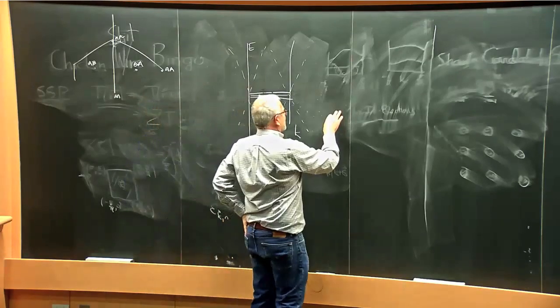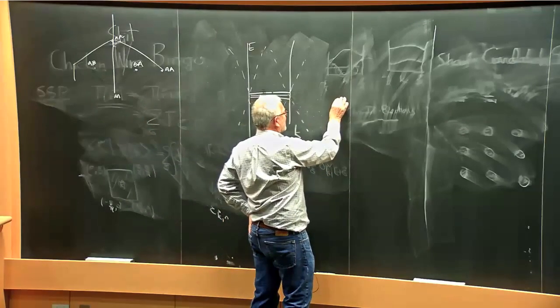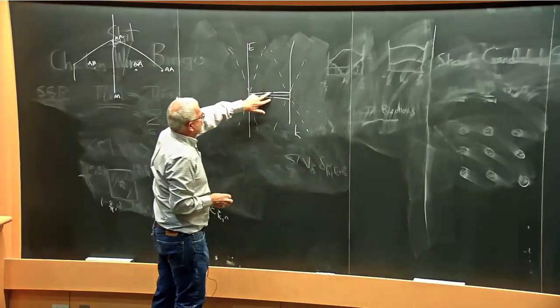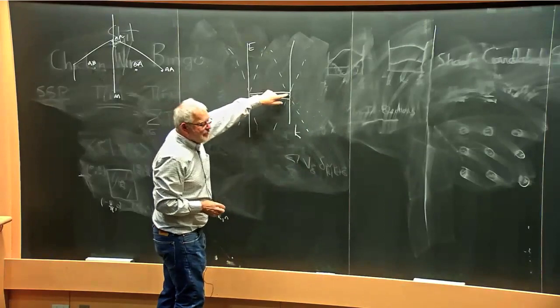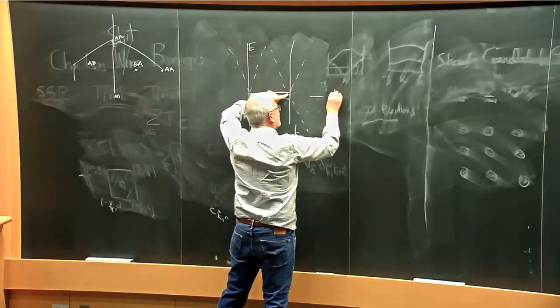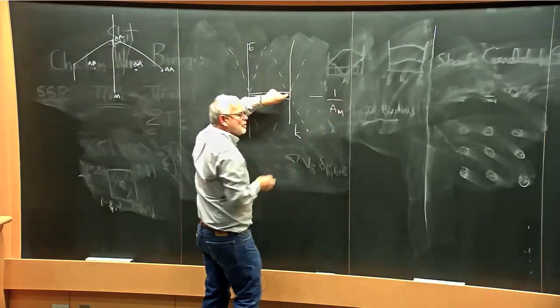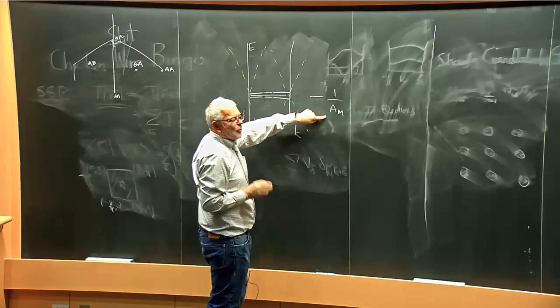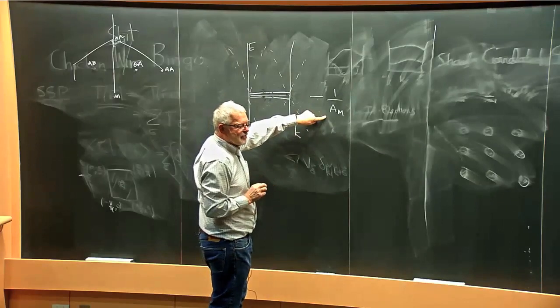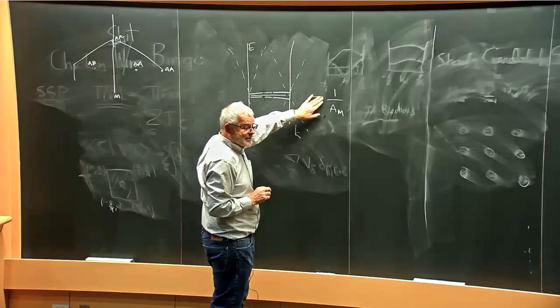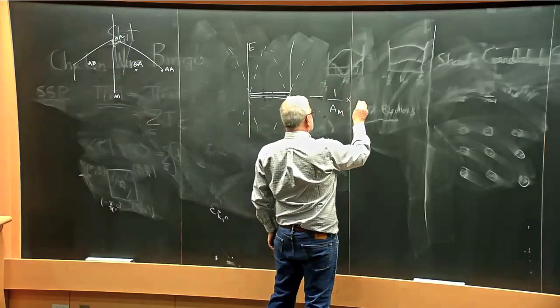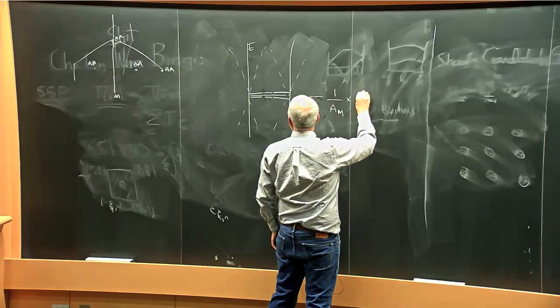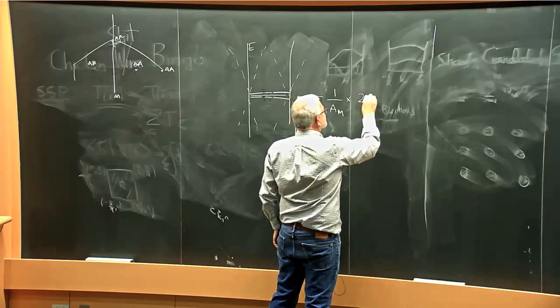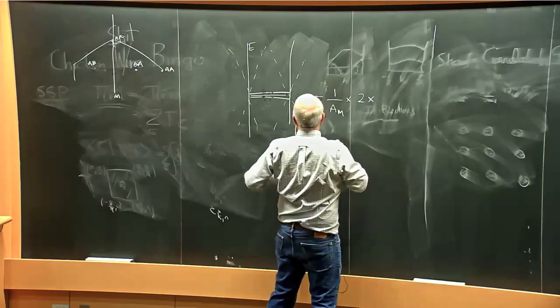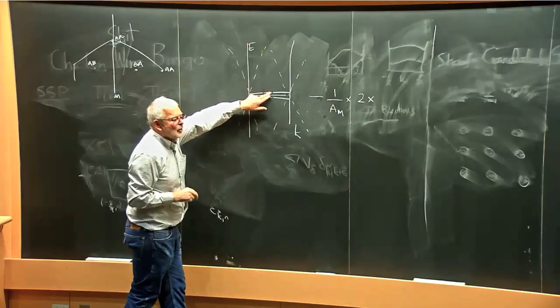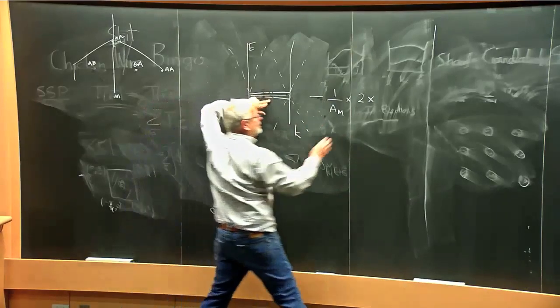And so this occurs, the number of electrons that fit in these bands is 1 per Moiré unit cell. That's 1 for every 10 to the 4th to 10 to the 5th carbon atoms. Okay? But it's also important that there are 2 spin states for every electron. Also, it turns out that instead of having 1 dispersionless band here, you get 2.